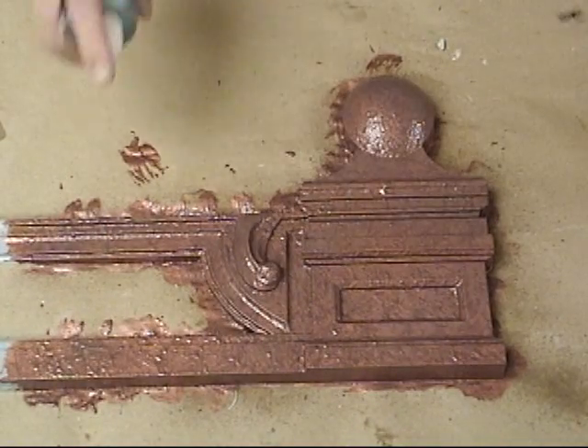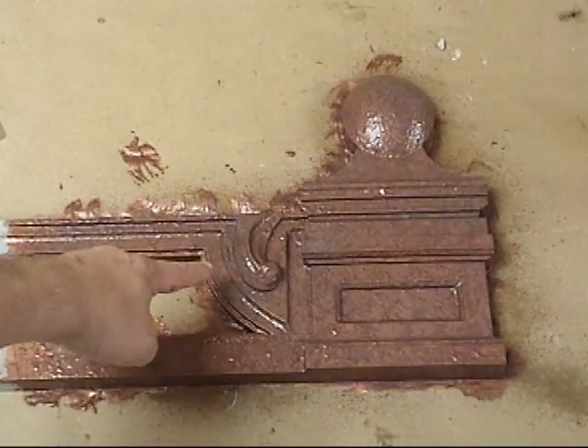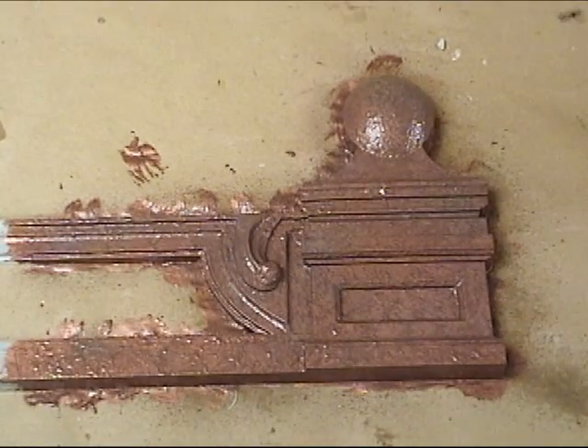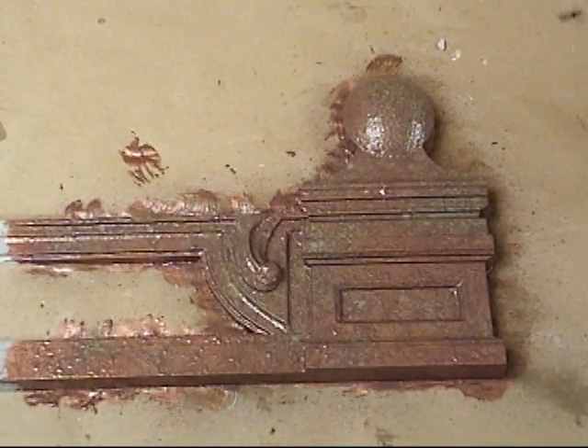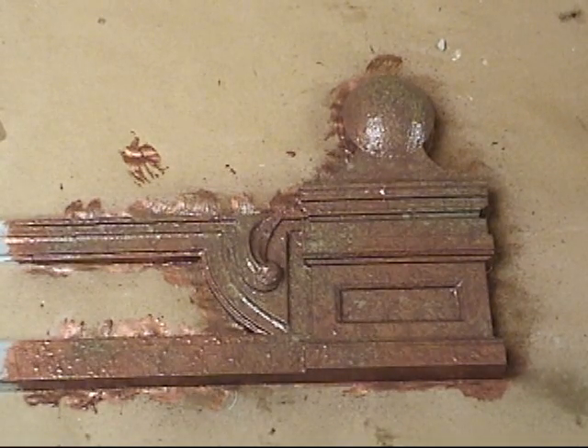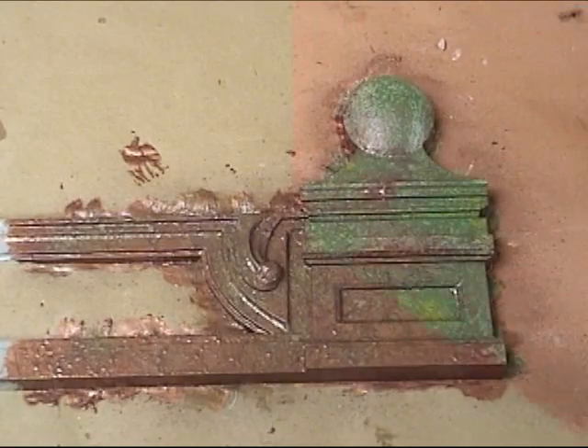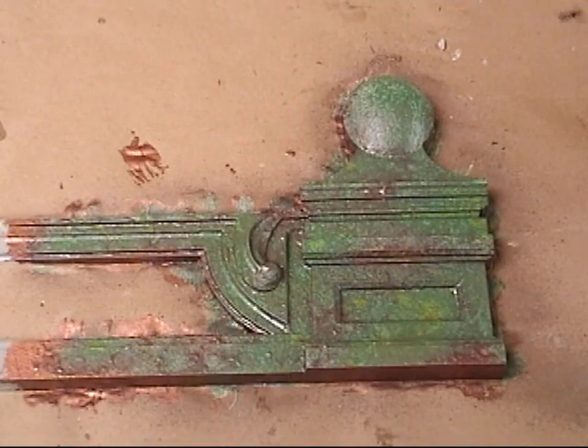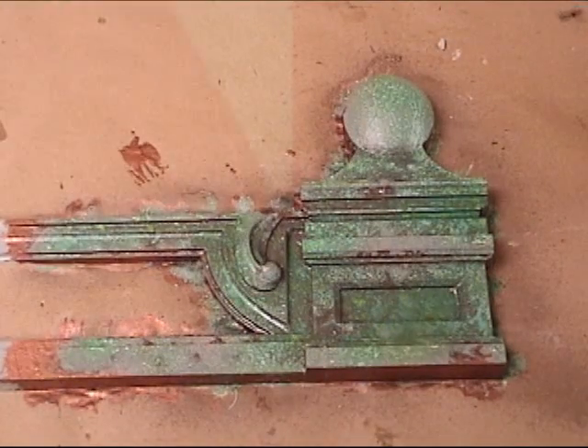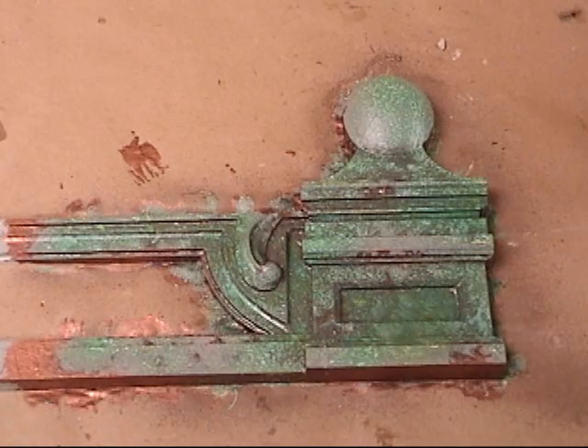Now as soon as we spray this on, now I did this in a fairly humid environment, and you'll notice that we're already getting a reaction just minutes after the spray application there. And a few minutes later we're already seeing the greens develop. And this was after about 20 minutes. We got a really good reaction. And you notice that light green starts to really change in about 30 or 45 minutes.